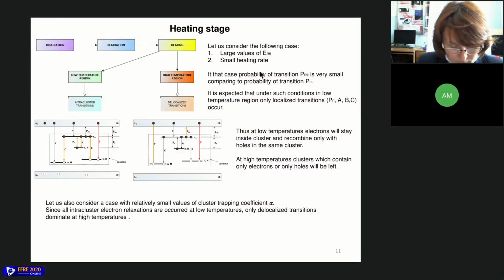Let us consider some analytical estimations before simulation results are shown. We'll describe the limit case when activation energy ENE is much larger than activation energy N and heating rate is small. In that case, the probability of transition PNE is very small compared to the probability of transition PN. Also, we consider a case with relatively small values of cluster trapping coefficient alpha.